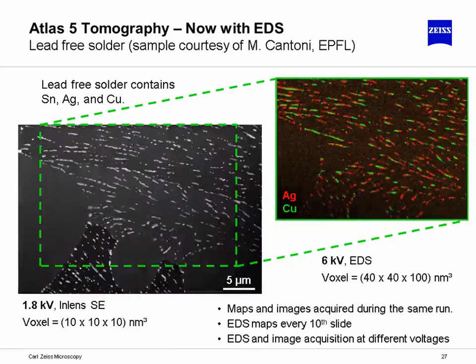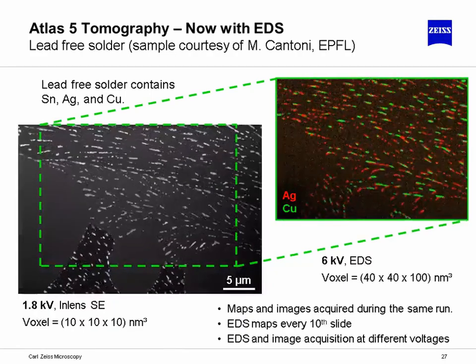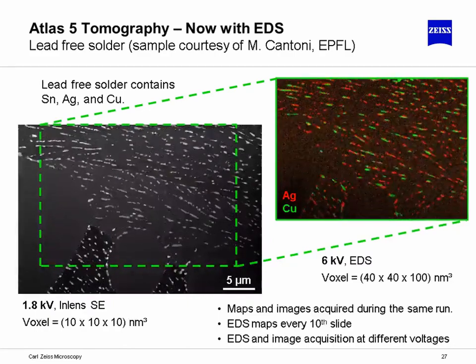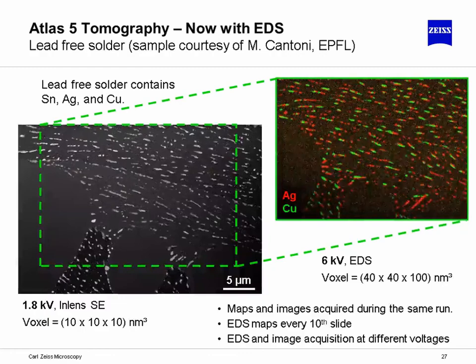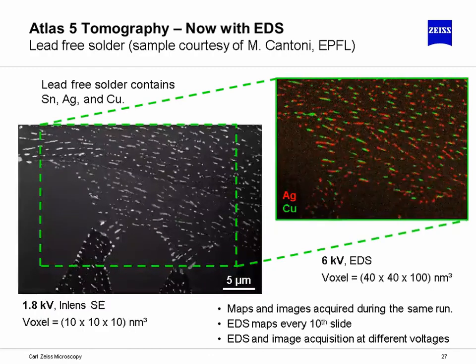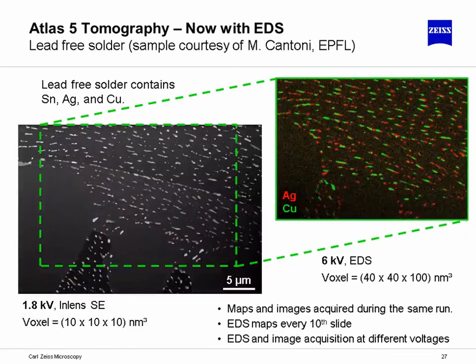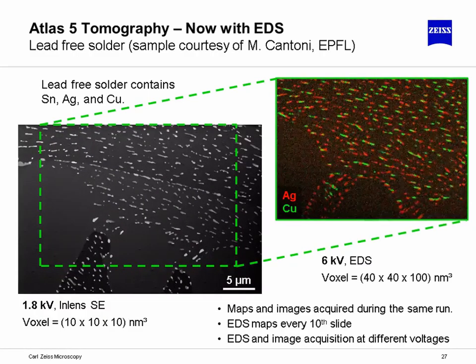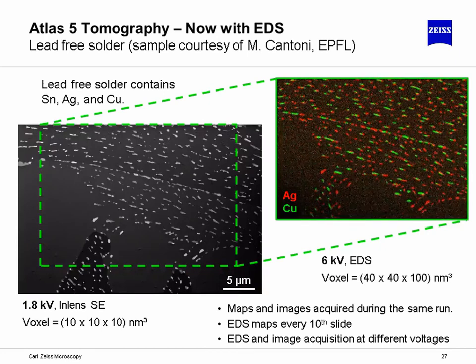On the left movie, you can see the in-lens SE signal. The images were acquired at 1.8 kilovolts. The voxel size is 10 by 10 by 10 cubic nanometers. On the right side, you see EDS maps that were obtained from the region that has been framed with a green frame. The EDS maps were acquired only every 10th slice, because the information depth of the EDS signal is larger than the in-lens SE signal. What's important to note is that the EDS and SE images were acquired at different landing energies of the SEM.